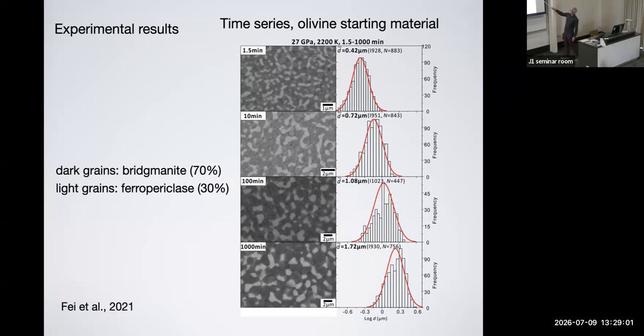And you can see that if you look from 1.5 minutes, right, so you barely reach temperature and then quench, to 1,000 minutes, you can see that here's the grain size distribution, right? It's a nice normal grain size distribution. The mean grain size increases over time. So that's your normal grain growth. That looks very nice in these experiments.